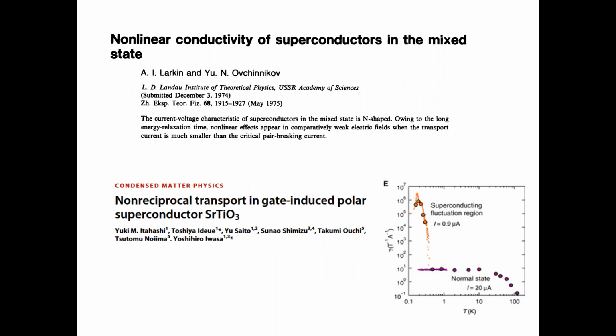So this is strontium titanate. And here I plot again this magneto-chiral coefficient that I showed you earlier. You take a non-centrosymmetric material, you apply a magnetic field, and you can look at the non-reciprocal resistance. You see this coefficient is small at temperatures far above the superconducting TC, when it's away from the superconducting fluctuation region. But as it enters into this superconducting fluctuation regime, you see this non-reciprocal coefficient increases by several orders of magnitude.